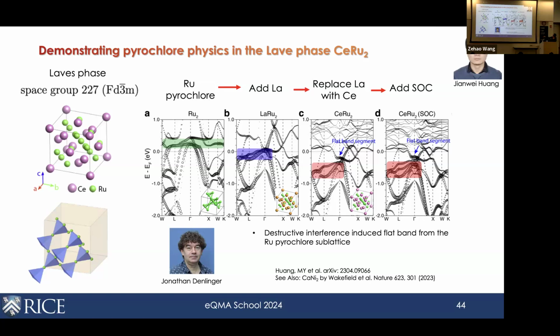Then the next step is to replace the lanthanum with cerium. You see the additional carriers introduced in the substitution, and then eventually, if you incorporate spin coupling, we can recover these DFT calculations for the actual material. We can track that these are the states, including this little portion, which originate from the flat band associated with the pyrochlore lattice.